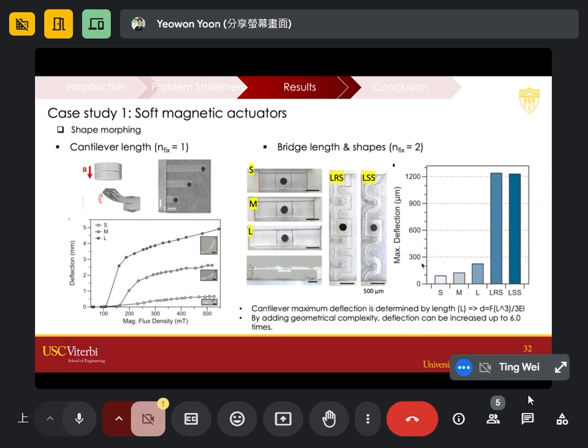As I said, this is soft magnetic powder, so it responds to a magnet. The magnet, which is a hard magnet, usually has a gradient of magnetic field density. So if you approach the magnet, this cantilever beam is attracted to it. We were thinking of using it as a soft actuator. Here I printed a few samples with a shorter length, then a middle and a large cantilever suspended structure, where the longest beam has the maximum deflection, and the shorter beam has a smaller deflection.